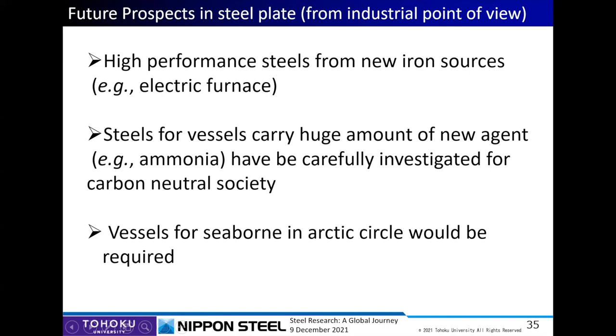Yes. The most important thing is we have a higher concentration of nitrogen in electric furnace steel. Also, we have some higher concentration of impurities such as tin, phosphorus and sulfur. So we have to take care of such impurities and nitrogen. In steels made from blast furnaces, we can reduce the nitrogen, but in electric furnaces, it is still a bit difficult to reduce such nitrogen and so on.